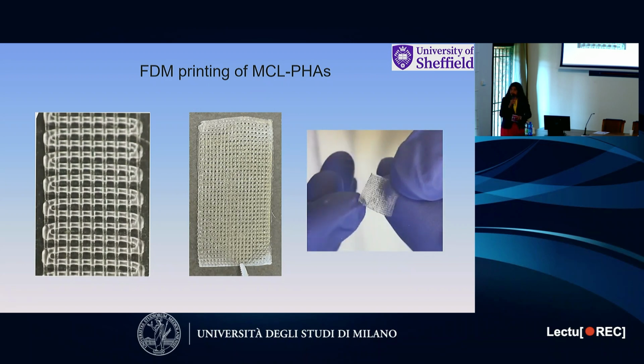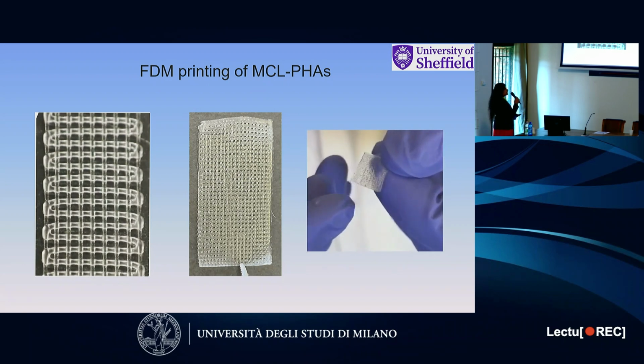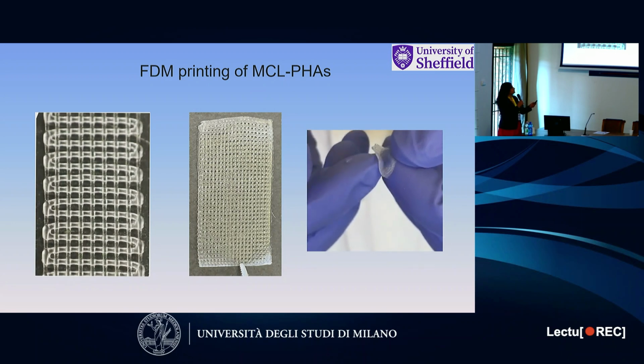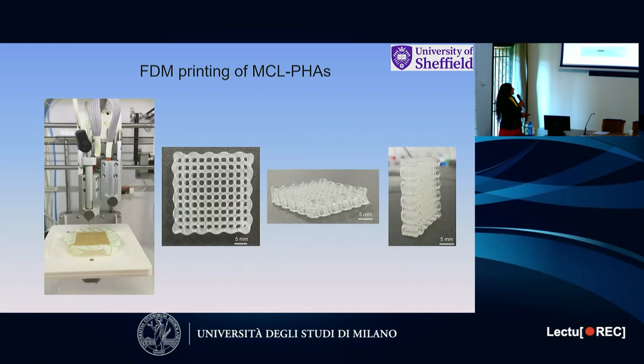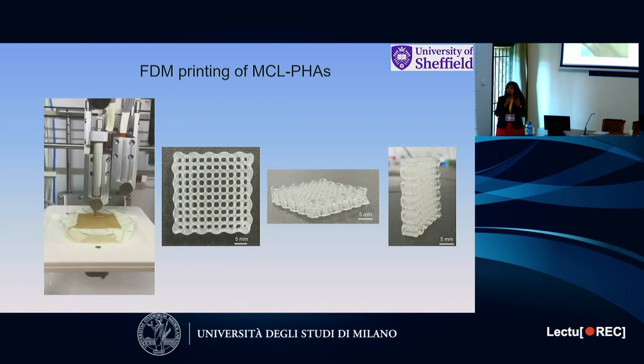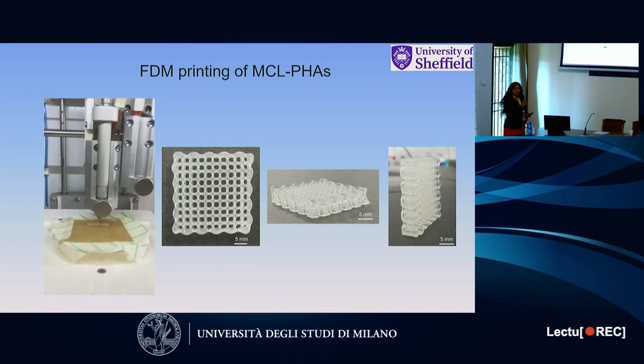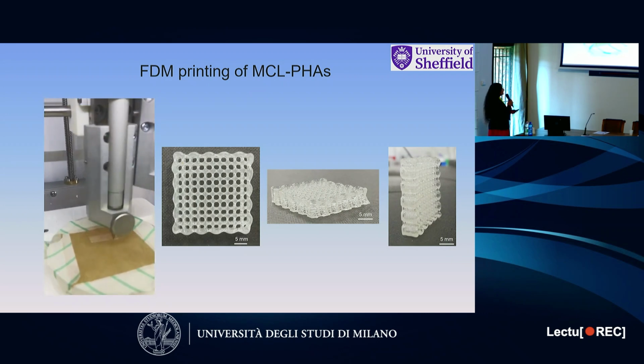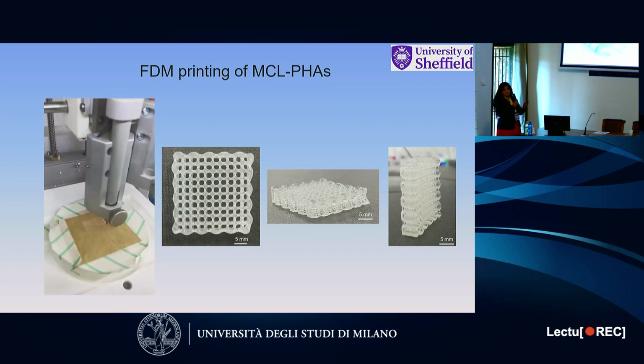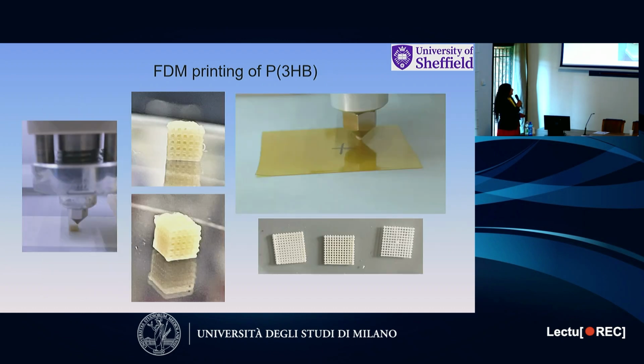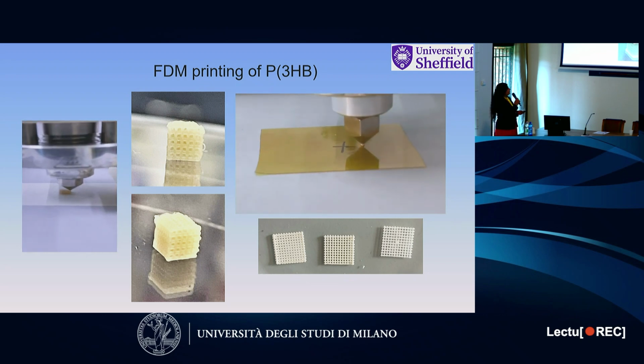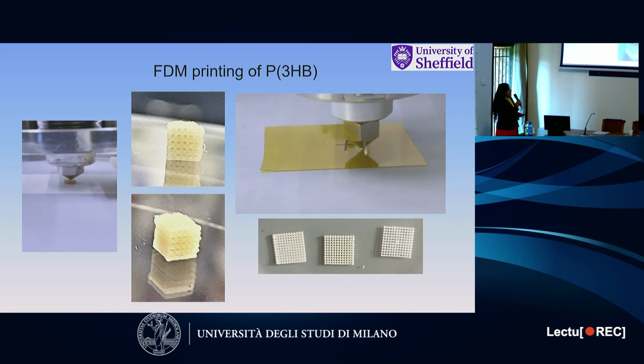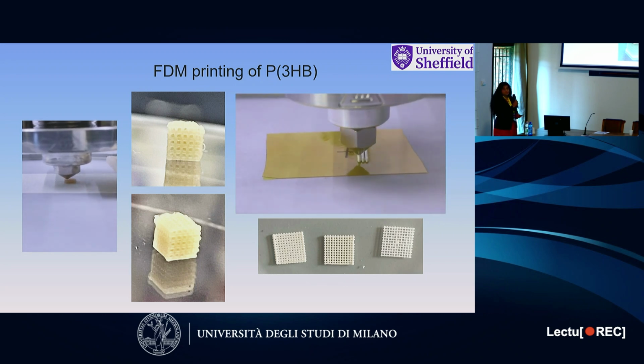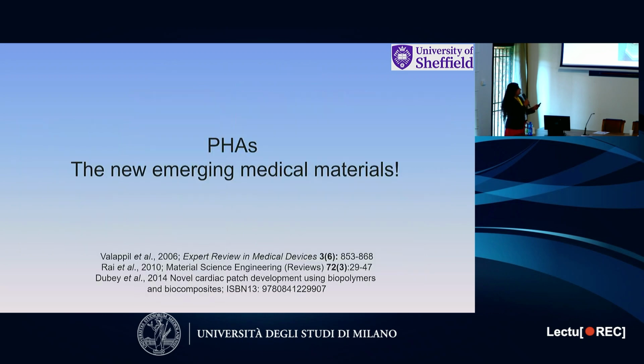Here's FDM printing, fused deposition modeling, of the medium chain length, the highly elastomeric, and you can see how elastomeric that polymer structure is. And this is another one, like I said, I have many different types of medium chain length PHAs. This is yet another one where we created a slightly bigger structure because this was for bone. And this is PHB, which is the rigid form. Many people cannot print PHB. We have some tricks up our sleeves, and therefore we can print them. This is on its own, and on the right you can see it's a composite with a particular additive.